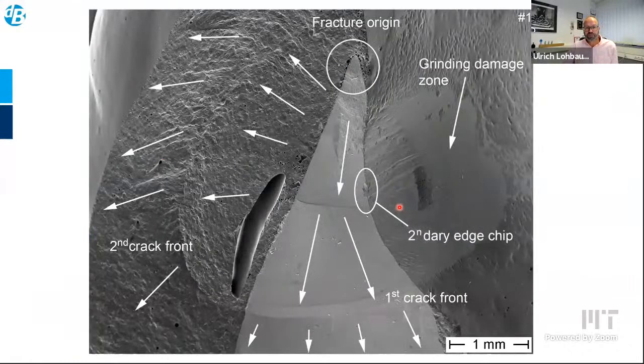top of the zirconia. When we further go down and analyze, we see this white grinding zone on the inner side, but when we have a chipping defect, this could be a failure origin. But once we really analyze and we see the twist hackles here, the arrest lines there, the wake hackles and all the hackle lines here, we can actually trace back the fracture event up to this region. And in the end, it was a wetting problem here. Of course, it's a problem of the tip here. This is certainly not what you do with a ceramic material, but also the wetting problem here, the pores around the tip, they were responsible for fracture of this bridge.